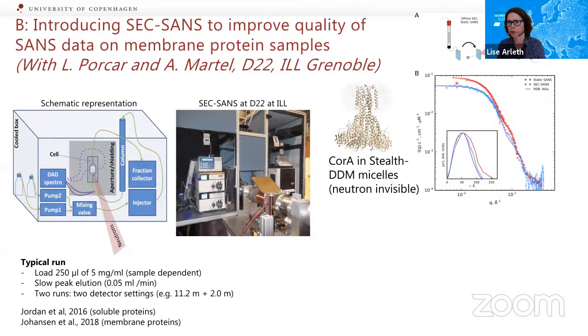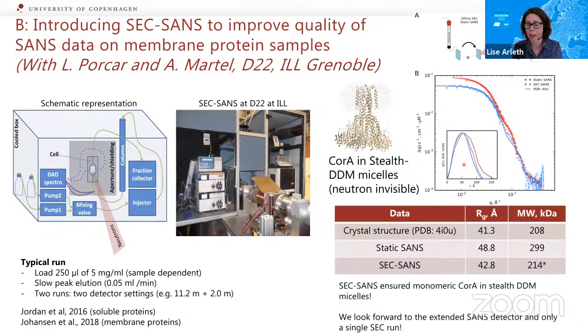And if you compare these two plots, this should have been the same sample, but as you can see, there's more scattering from the offline SEC-produced samples, and this is a typical sign of aggregation of the sample. So this really shows us that we obtain much better samples with this online SEC-SANS approach. Also, despite having less good statistics, the sample is much better. So this is an important improvement.